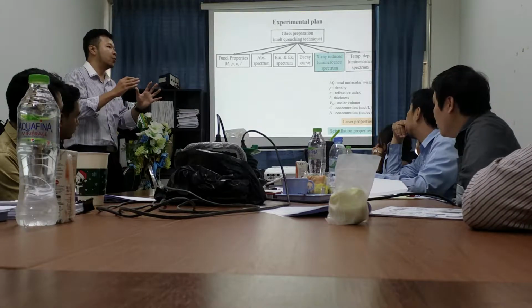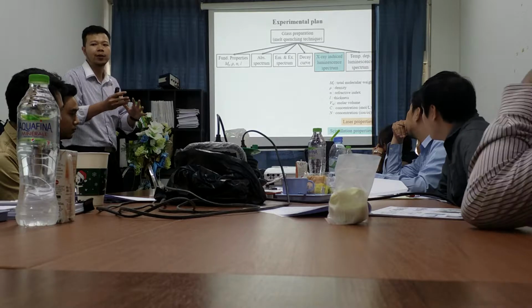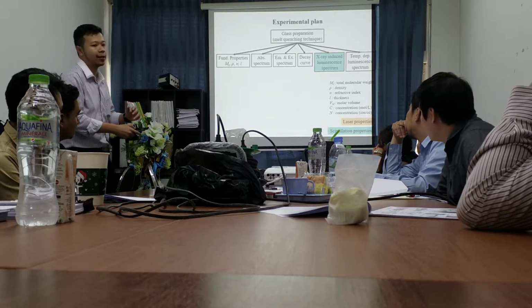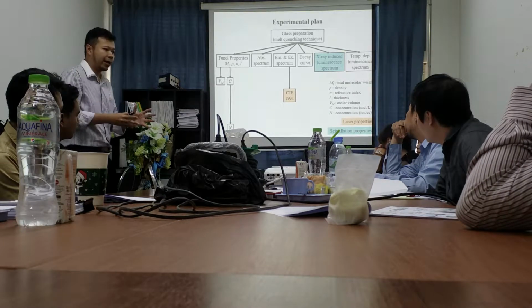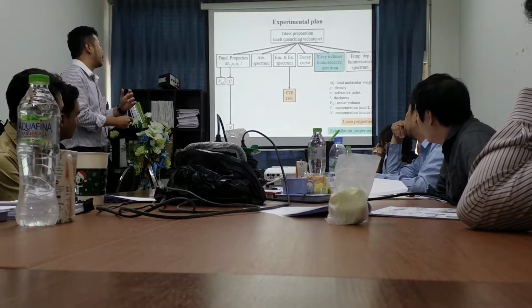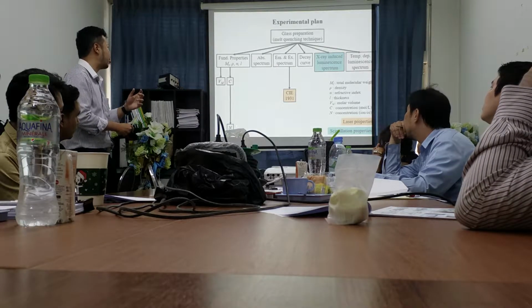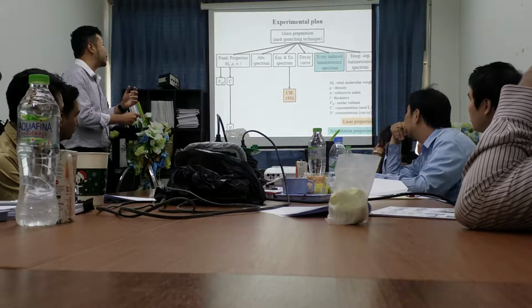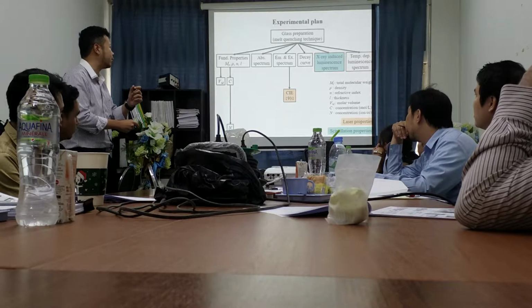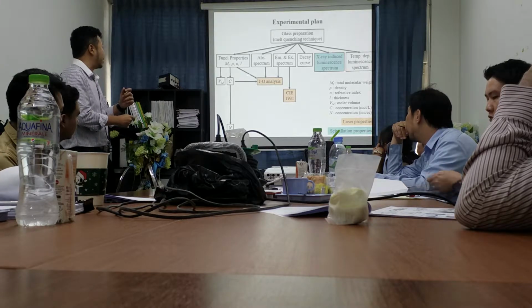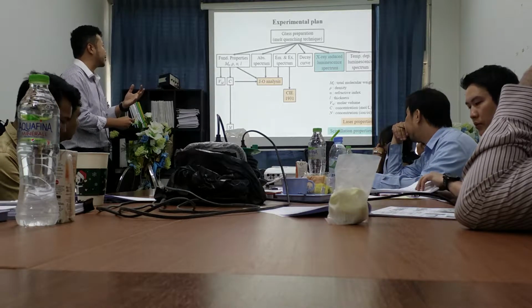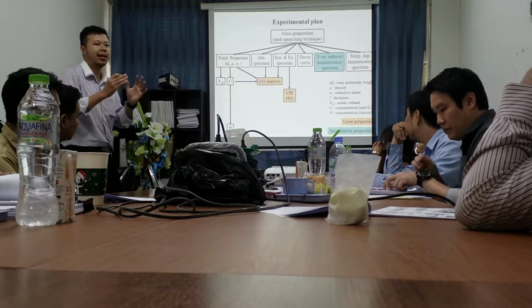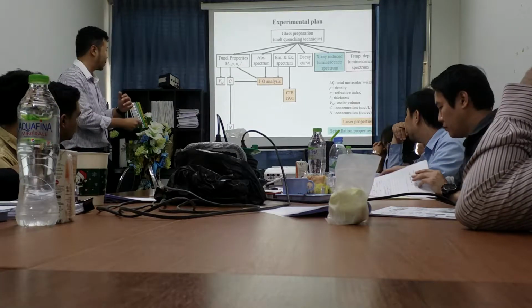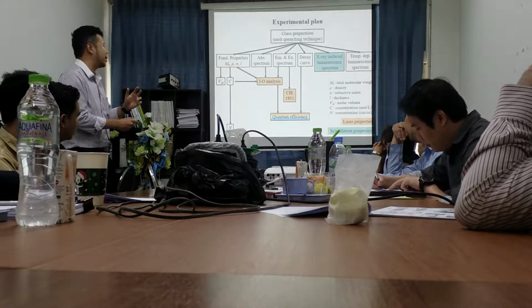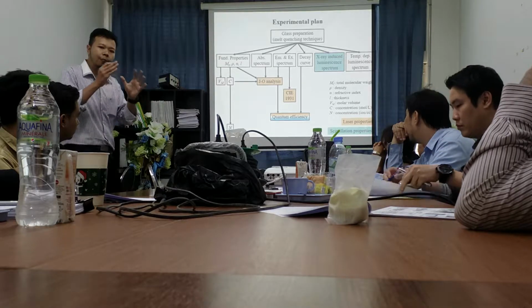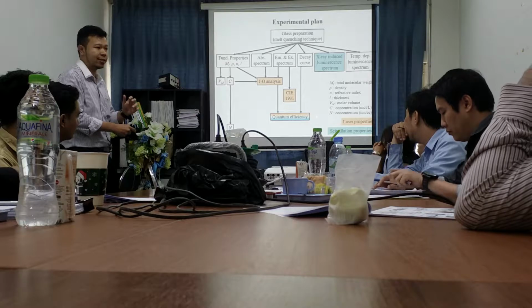And finally, I study the effect of temperature on the luminescence property of the glass by measuring the temperature dependent luminescence spectrum. Next, I calculate and analyze the molar volume, the concentration of the lanthanide oxide, and the ion concentration of the lanthanide ions. And I take the emission spectrum to find the emission color on the CIE 1931 chromaticity diagram. I take the values of the fundamental properties, absorption spectrum and emission spectrum to analyze the laser potential by using the Judd-Ofelt analysis. The calculated lifetime and the experimental lifetime from the decay curve were compared to evaluate the quantum efficiency.